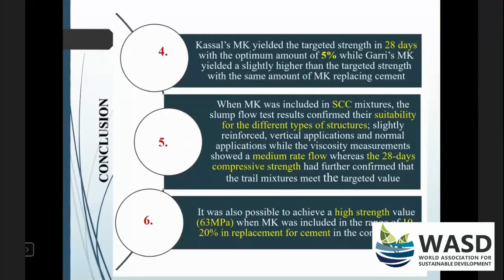And when we had the metakaolin included in self-compacted mixtures, that was interesting. All the slump flow test results confirmed the suitability for the different types of structures being slightly reinforced for vertical application or normal application, while the other test, which is the viscosity measurement, showed a medium rate flow, whereas the 28 days compressive strength had further confirmed that the trial mixtures meet the targeted value.